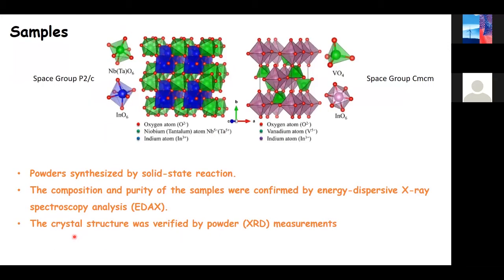Okay, so which samples have we used? The samples we have used have been prepared by some of our collaborators. They synthesize powders by solid state reaction. We checked the purity of this powder. They were high purity. We checked it by means of EDAX measurements. We checked that the crystal structure is the one expected, and we did it by powder X-ray measurements. All these measurements were done at ambient conditions before loading the samples in the diamond anvil cell.